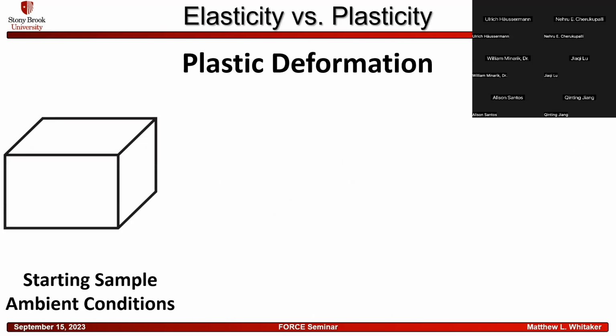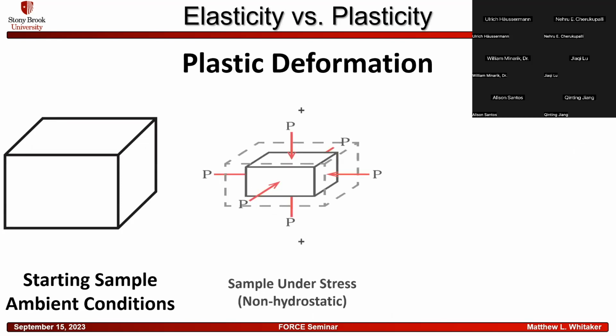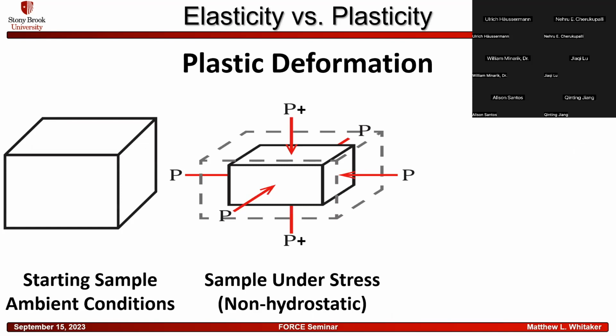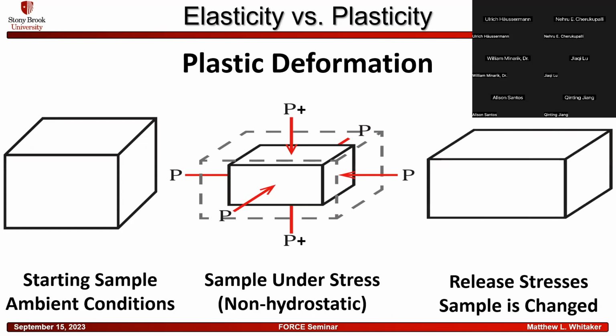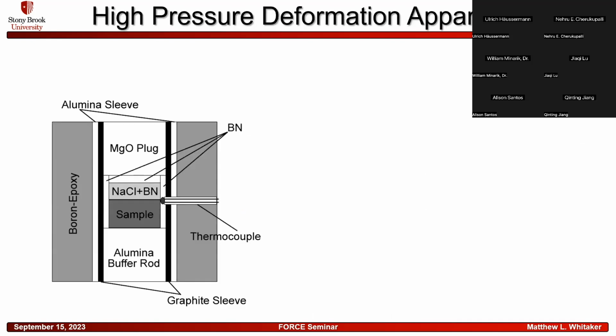You have a starting sample under those same ambient conditions, but you have pressure that's higher in one direction than another. More force is being applied in one direction than the other two directions. And what that means is when you release the stress afterwards, the sample is changed. It's not the same shape and doesn't have the same properties as when you started. So this type of apparatus is what allows you to study that.